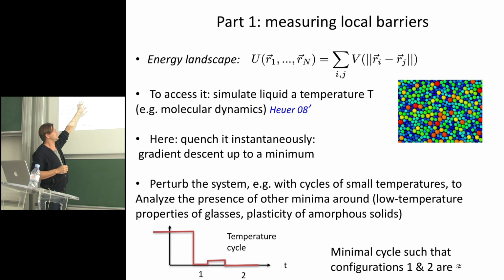So the methods we'll use, and I will tell you it's used in other fields, we're not really inventing that, is to quench the system. So you take a liquid, you equilibrate it at some temperature, then you quench it to a minimum of energy, a local minimum, and then you do perturbation to study how you can excite the system and find new minima.